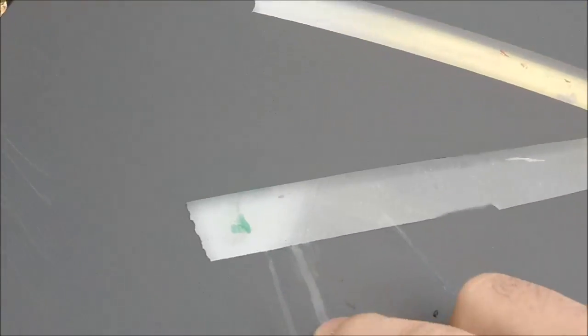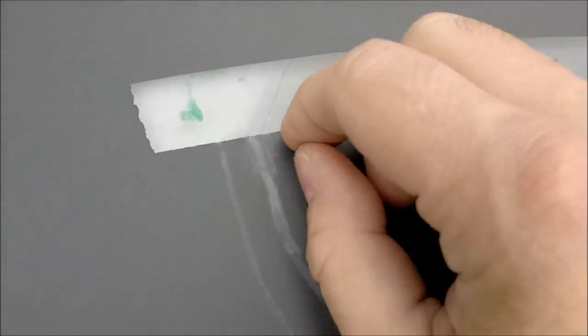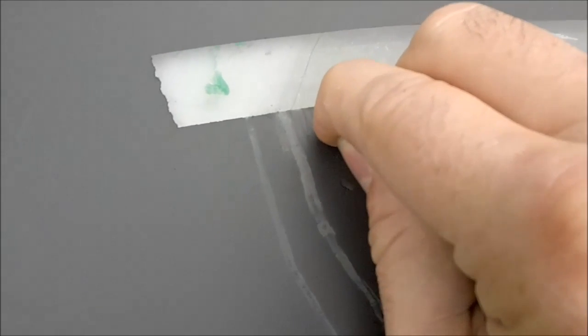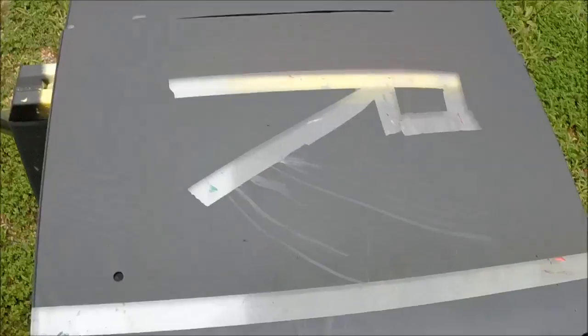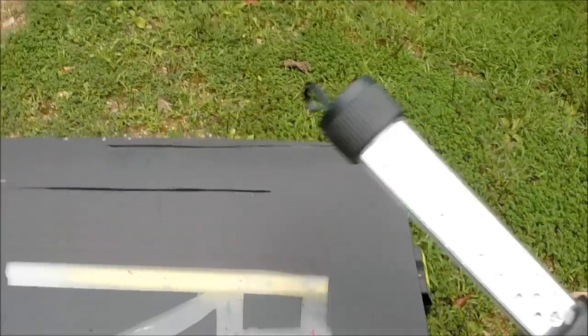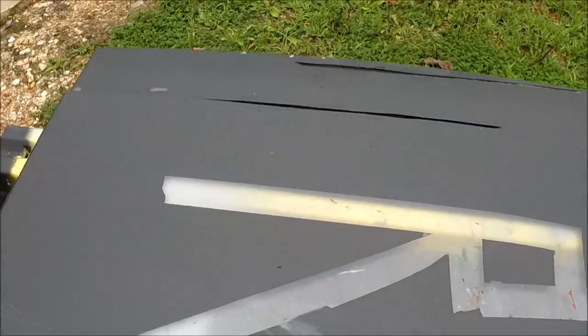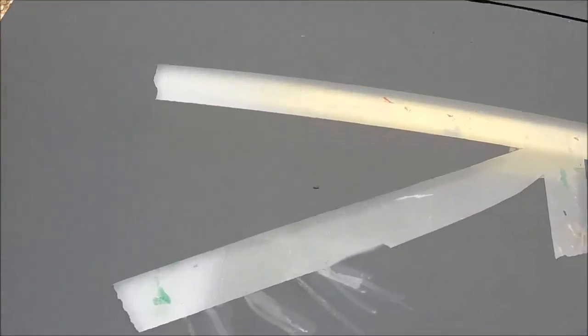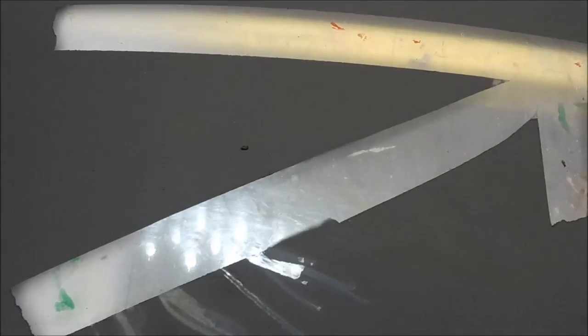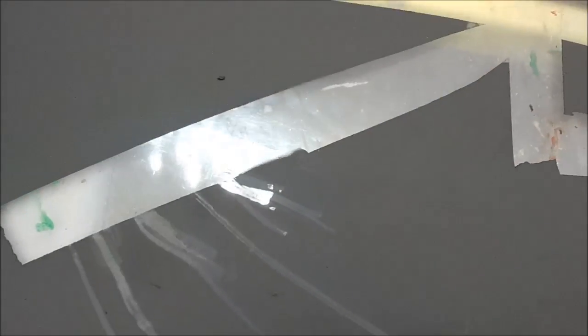I'm all the way through to the clear. Let me go get a light and I'll show you. I wanted to show you with this light—that's me removing the Rust-Oleum with my fingernails. It was that easy. I'm all the way down to the polycarbonate and you can see there's no bond.